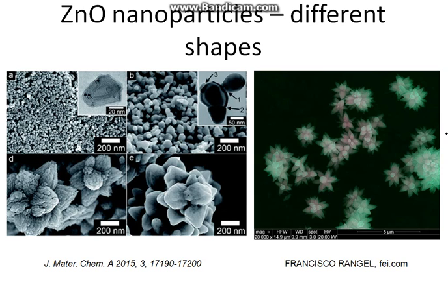So this is what I was telling you about zinc oxide nanoparticles, which can exhibit different shapes. Starting off with this image on the right, here you can see zinc oxide nanoflowers, and in this set of four micrographs on the left, you see an evolution of nanoflowers starting off from nanospheres. I should also mention that in this particular paper, these different morphologies are obtained as a function of heating conditions and also the coating that has been given onto the zinc oxide nanostructure.